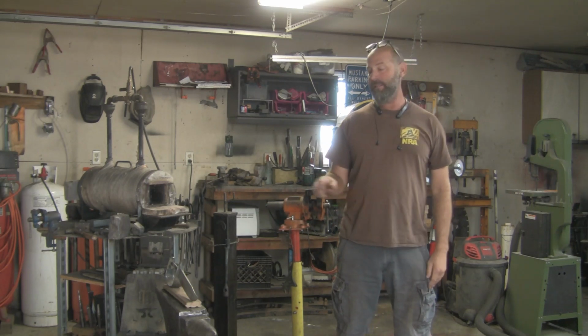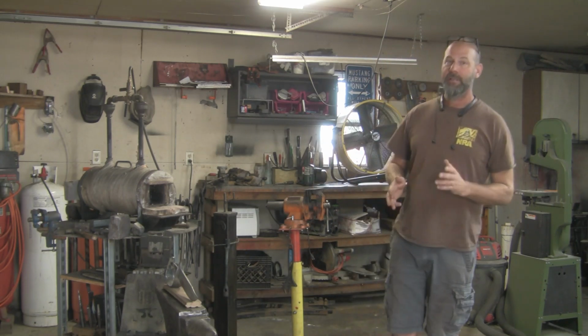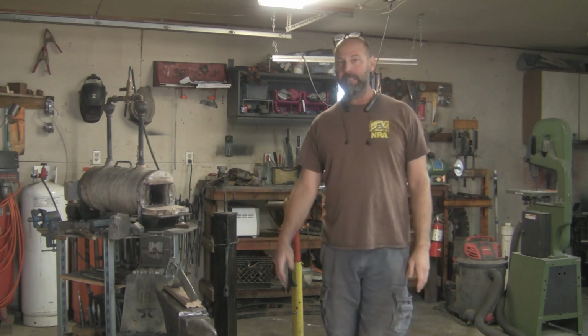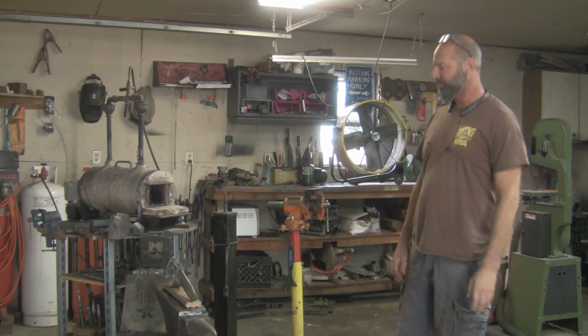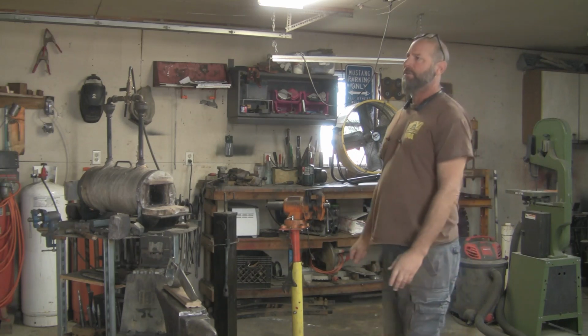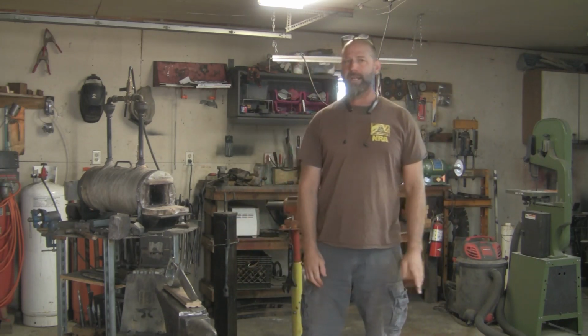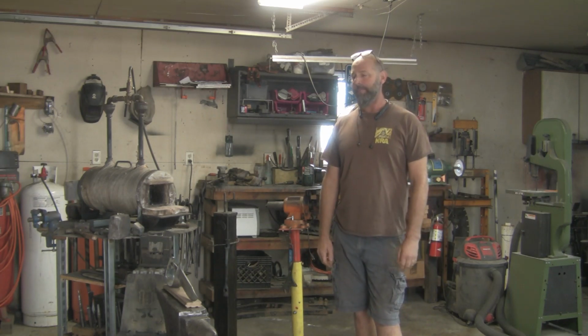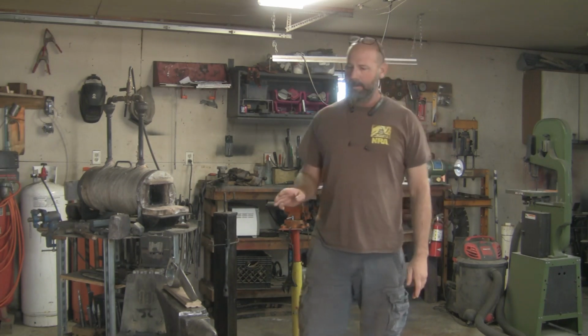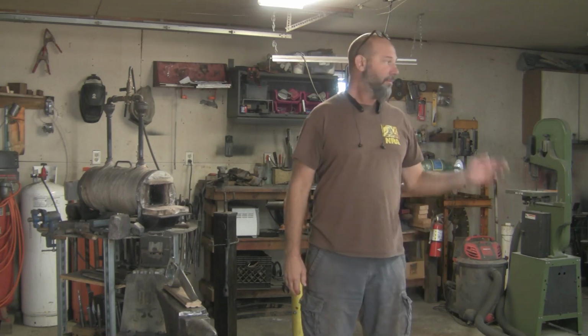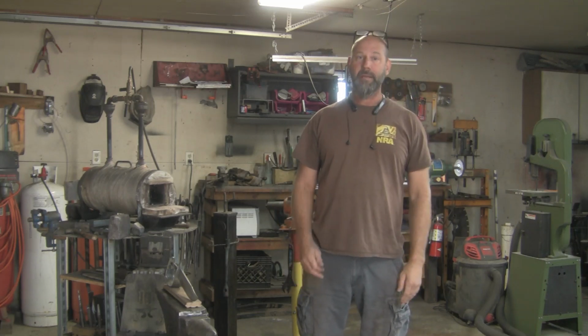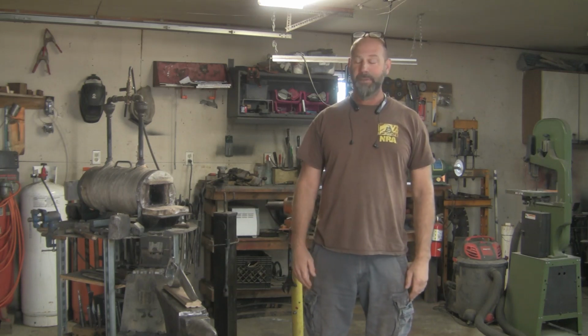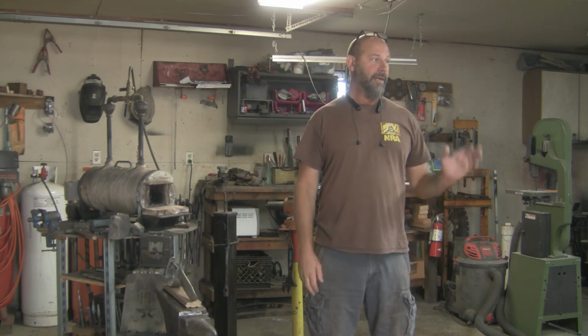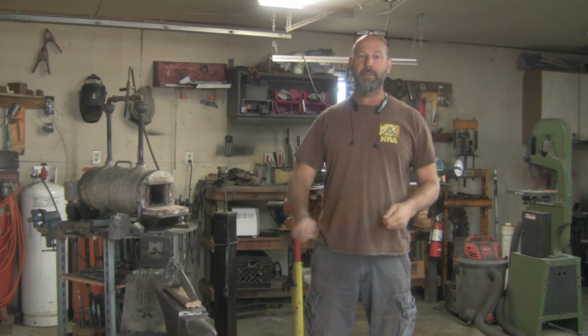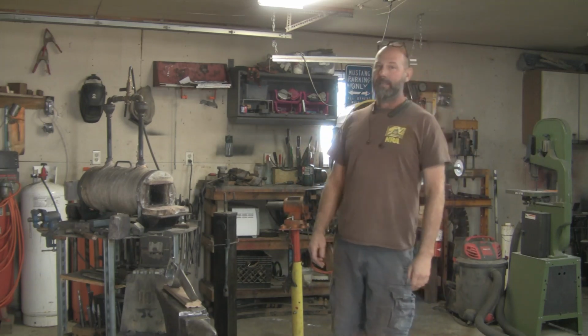Coming out of the etchant, I could see a line in it and a difference in how fast the acid was eating the steel because of the difference in the hardnesses. And the second concern I had was how usable a knife would actually be. So at that point, I went ahead and just took it over the belt grinder, threw a worn out 120 grit belt on it, put an edge on the knife, ran it on the stone a little bit. I got it to where it would at least pop hairs and shave a little bit, stropped it a little bit. And then I took it outside and did some chopping with it.